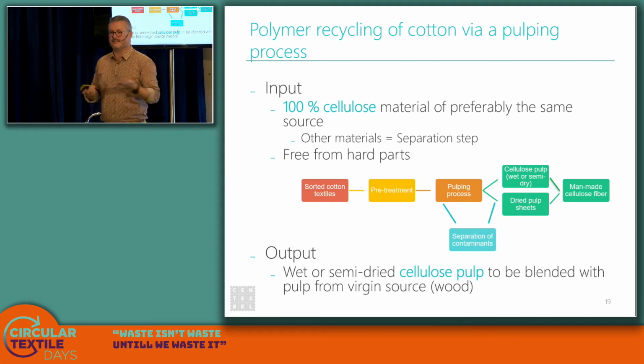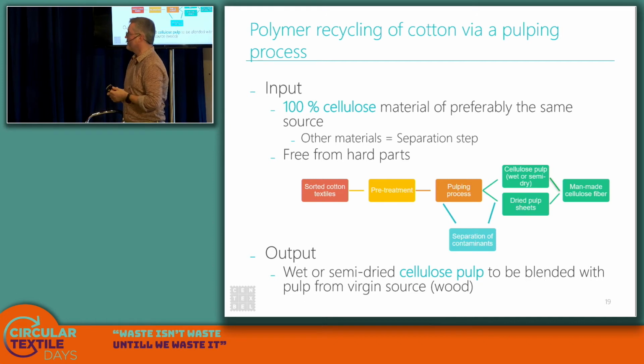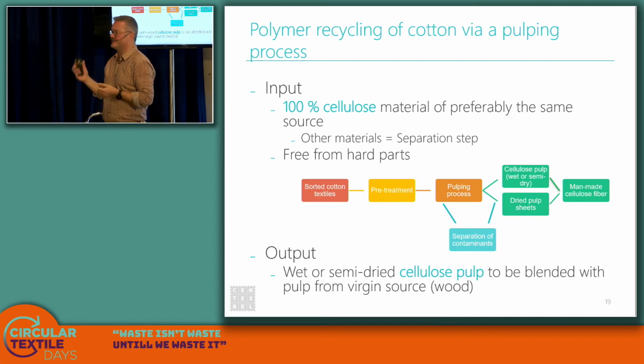So this is basically a viscose process. You grind the cotton, you make a pulp out of it, and that pulp is then blended in, because I didn't find anybody who has 100% recycled viscose or lyocell, depending on in which process you put it in. You can also have lyocell or cupro or another viscose type of fiber, but it's also always blended with virgin pulp. So there's still virgin wood or cellulose from a virgin source present. And not everything is possible, so not all the dyes are recyclable. There's still a lot of development needed within this process.